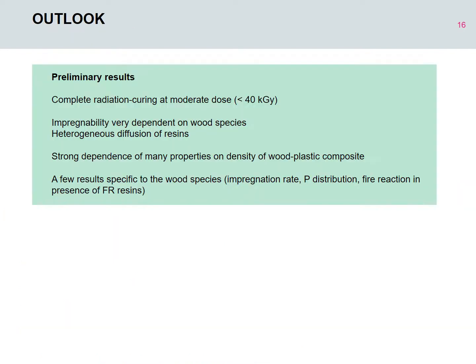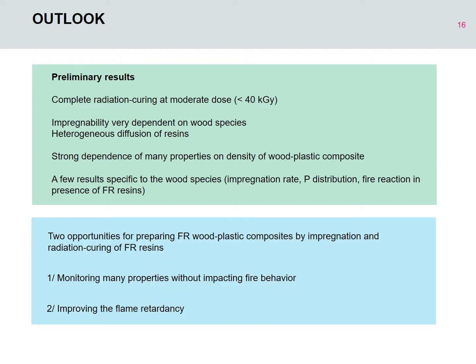This is only a preliminary result. We have shown it's possible to obtain a completely cured resin at moderate dose, lower than 40 kilogray. The impregnability is very dependent on wood species, and we have also observed a strong dependence of many macroscopic properties on the density of our composites. Of course, at this stage, the flammability of our composites is too high.